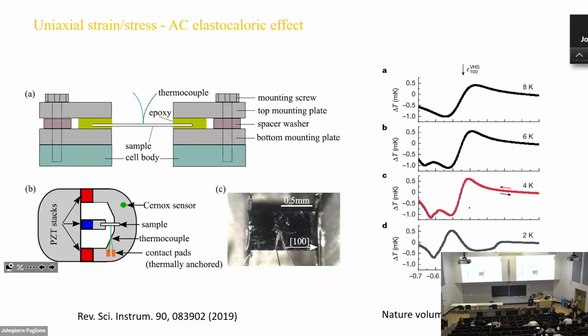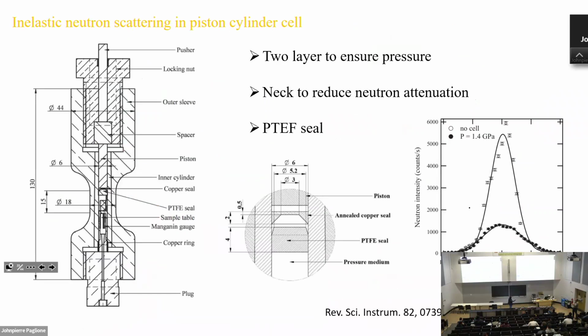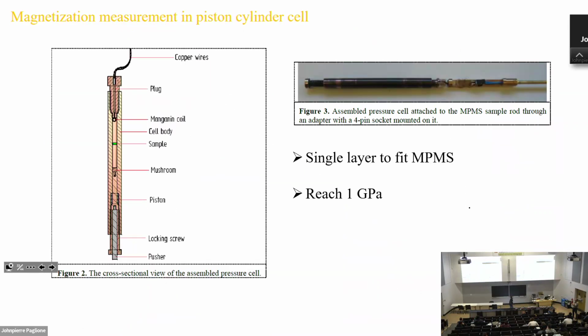Yeah, the clamp cell you showed is too big, right? No, the MPMS cell. The MPMS cell has to be non-magnetic, and you often have a background no matter what. You measure that background before, with no sample inside. The pressure is lower here also because you want a reasonable sample space. You could make that smaller and probably get a higher pressure, but then your signal goes down.